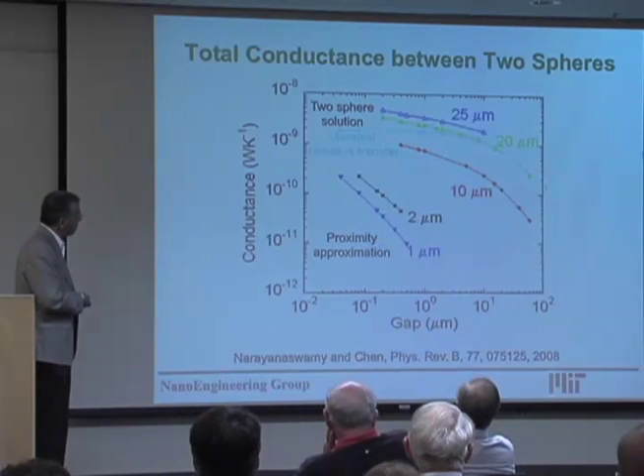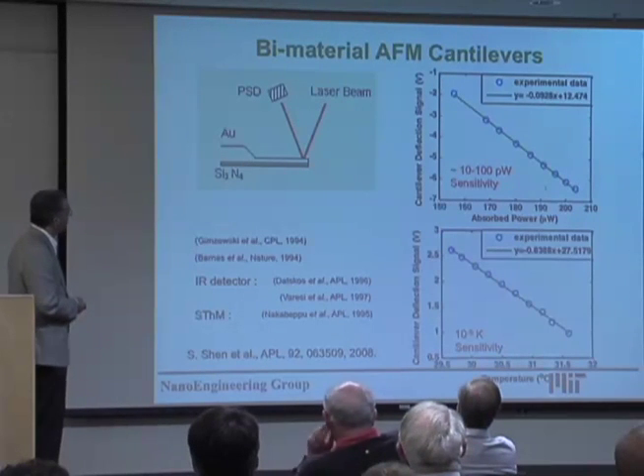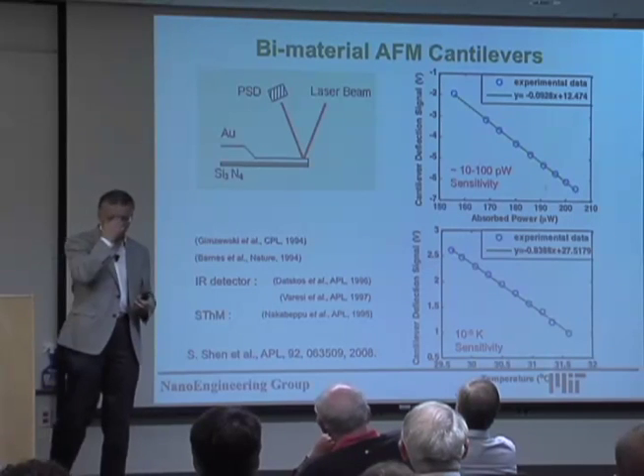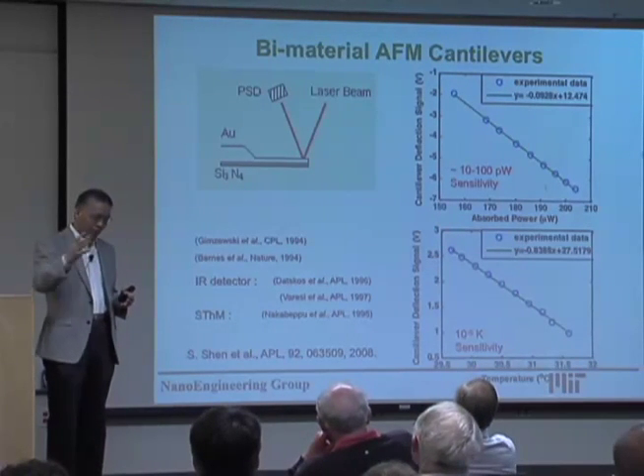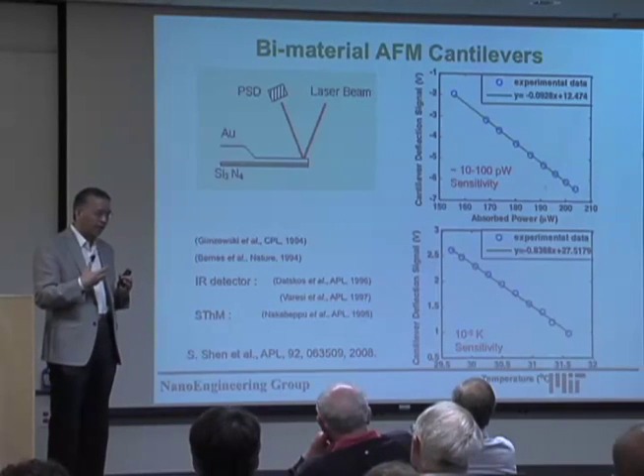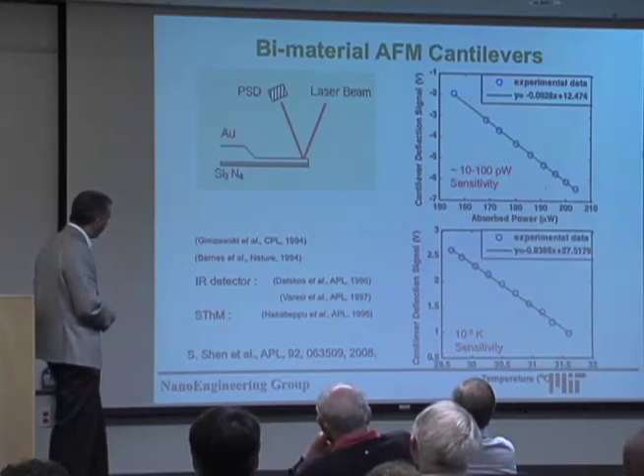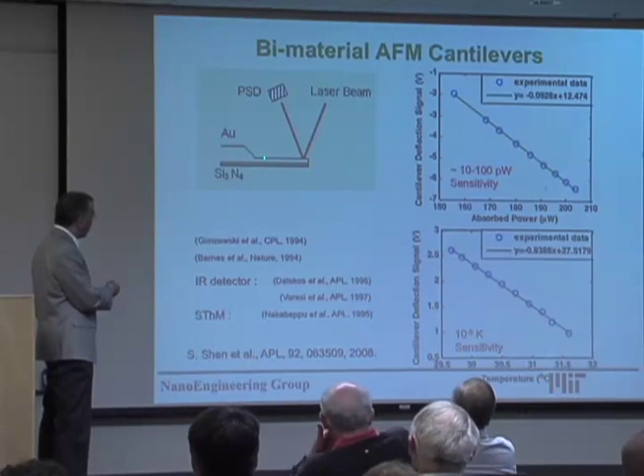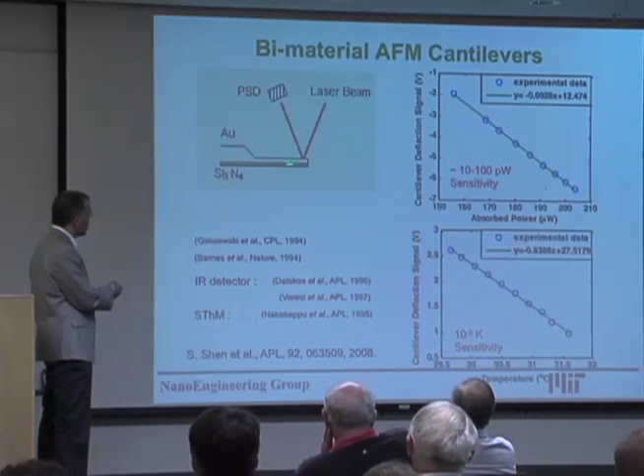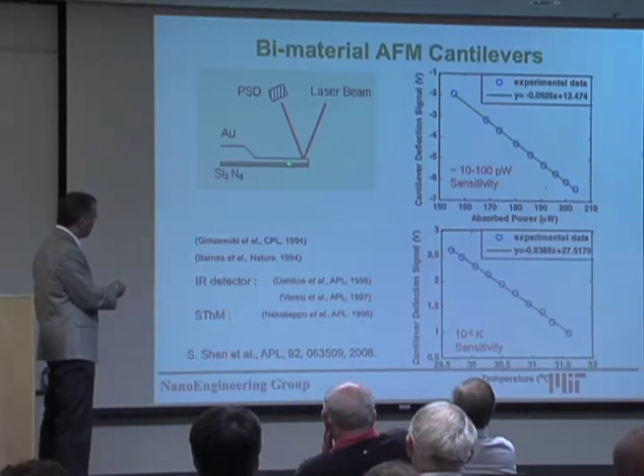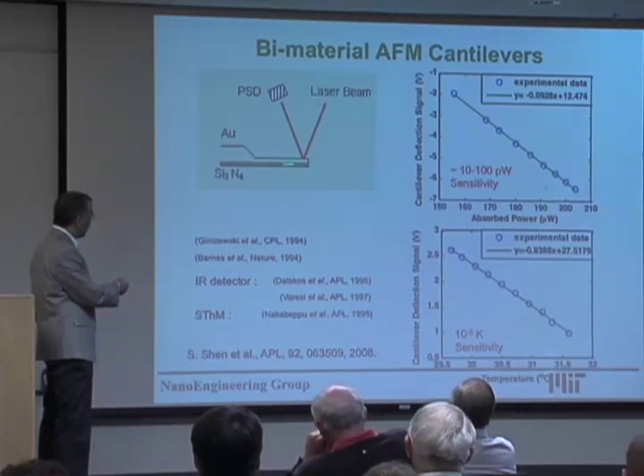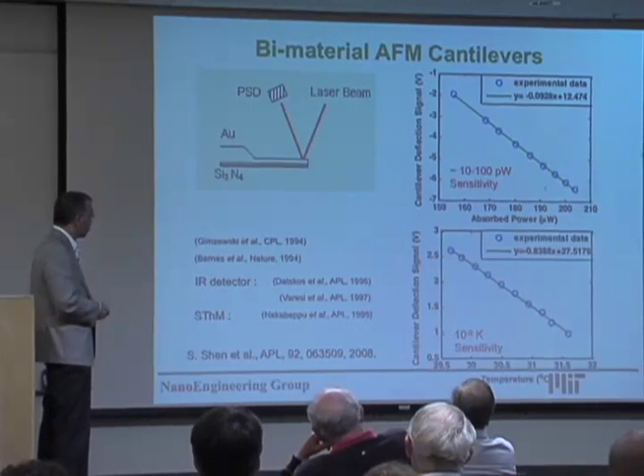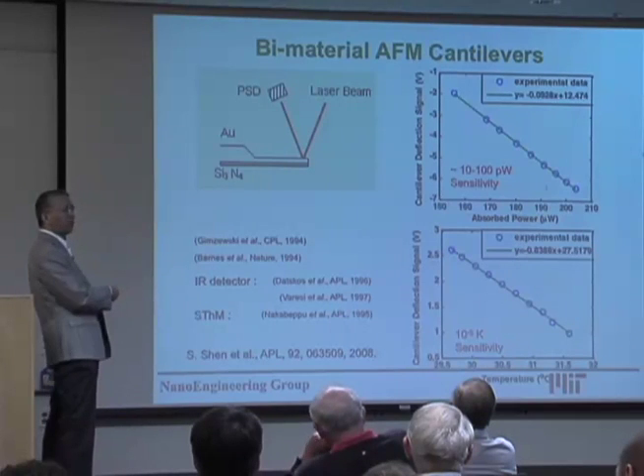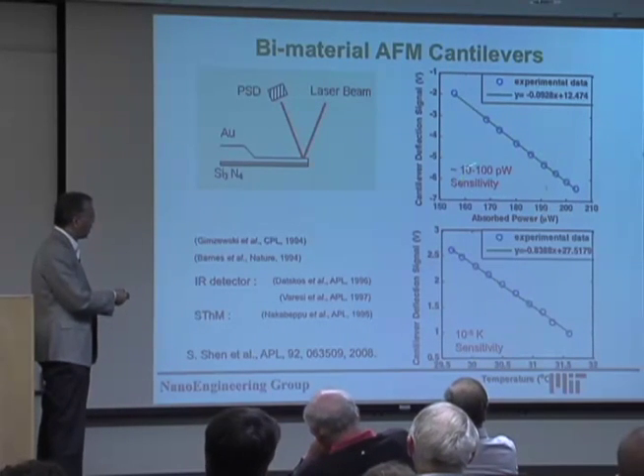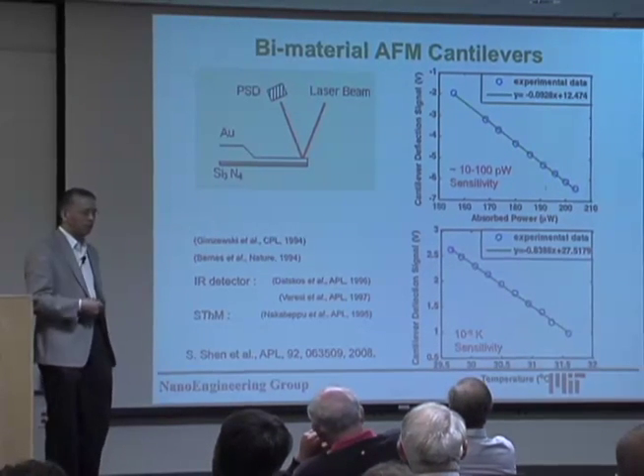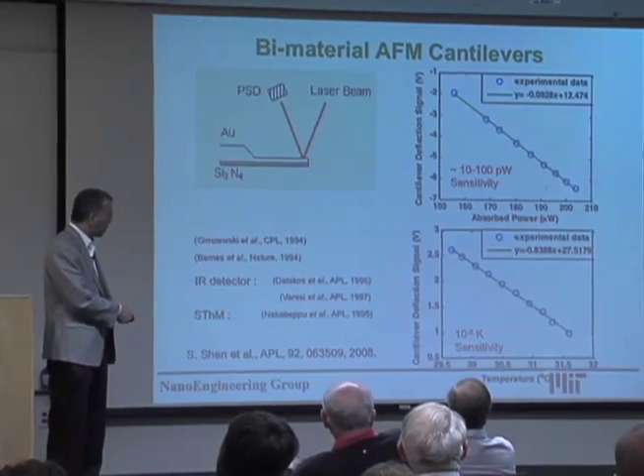The technique we turned to, probably some people are familiar with. I think there was a lot of work in Santa Barbara before, when Arun Majumdar was here, doing the bilayer cantilever as a thermal sensor. It turns out you can use an AFM cantilever with two different layers as a very sensitive thermometer, because of the thermal expansion mismatch between the metal and the dielectric cantilever, and a very small temperature change will create bending of the cantilever.